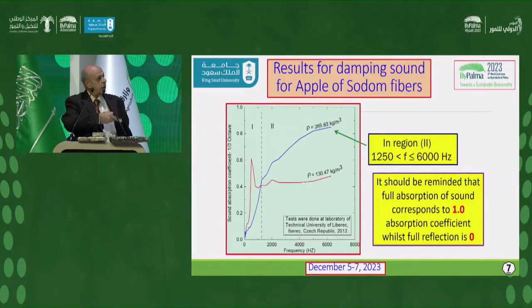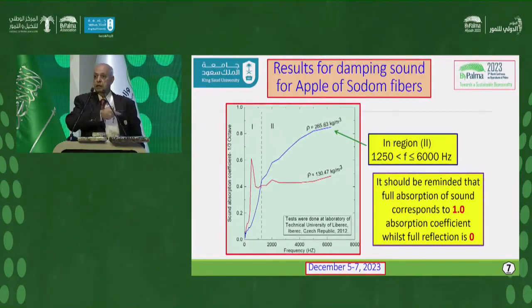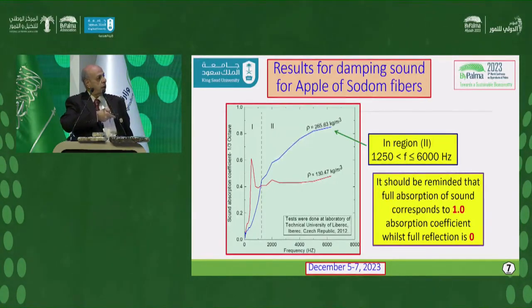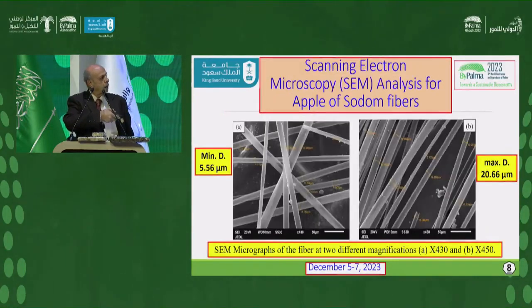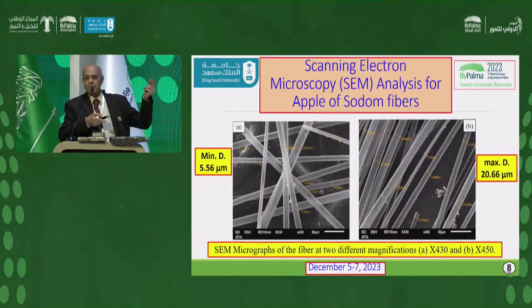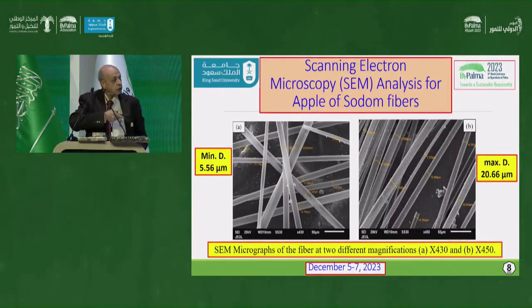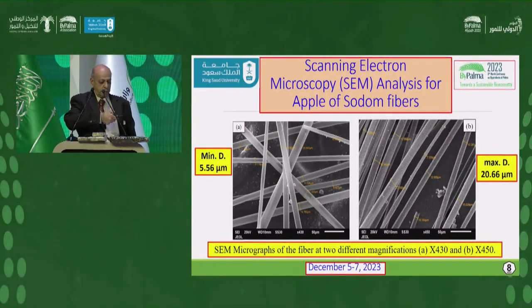Okay, this is the sound. We measure the sound absorption coefficient to see its ability to absorb the sound. The higher density one is good at high frequency, and the low density one is good at low frequency. The other one is good at high frequency. This is the fiber. It's very silky. It's like hair. The fiber diameter is between 5.56 up to 20 micrometers.